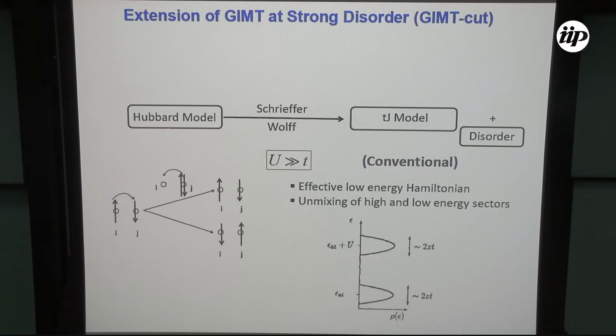What we did earlier was that we took the Hubbard model and did a Schrieffer-Wolff transformation. In the Schrieffer-Wolff transformation, as I was showing earlier, you have these virtual processes which are high energy, so you actually come back, which results in these spin flip processes, which give you the J term. So you have effectively two subbands which are clearly separated from each other by a difference of U, and we work in the low energy subband with no mixing between the two. This is just the Schrieffer-Wolff transformation. So we get a TJ model.